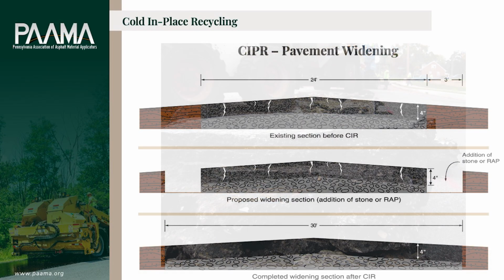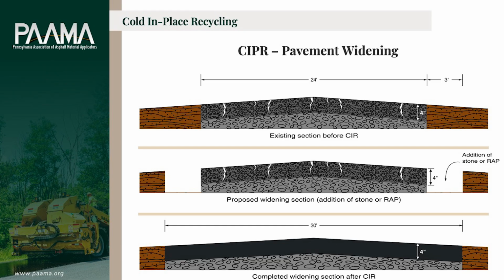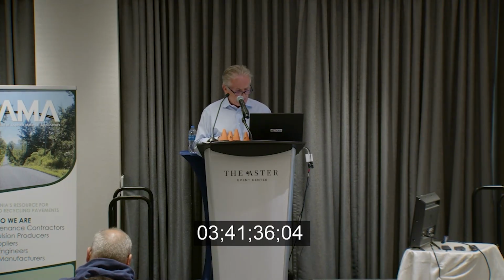If we're widening the road, basically we're going to take the two edges of the road, cut them down to where there's a stable subbase, put some drainage aggregate in the bottom of the trench, and then either put RAP or stone on top. What we do then is we would recycle from the center line to the edge of that widened area, and then the materials are a combination of the old road plus the new, whether they're virgin aggregates or RAP, mixed in together. So we mix in the cross shafts across the cutting mandrel, mix all those materials together. So it's not all stone that gets placed in there.